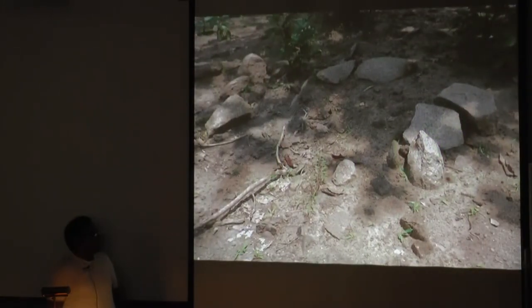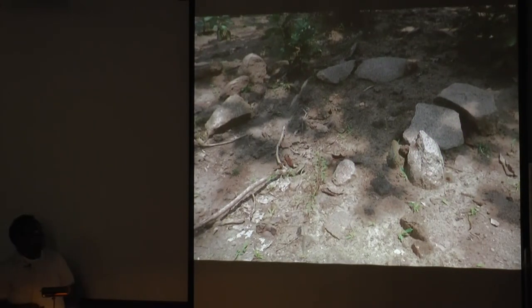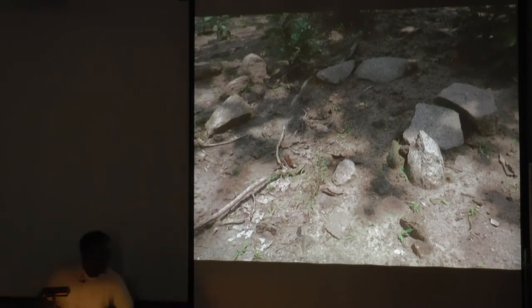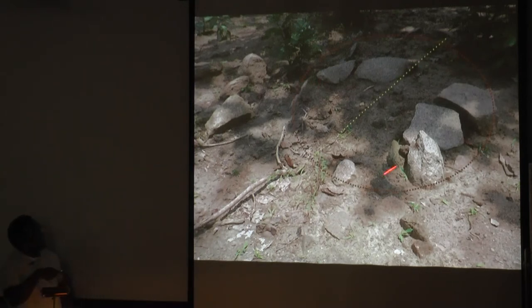And in there, because these sites are more or less intact, you would also see remains of furnaces like these. This was probably a furnace base supported by granite, and the place where the furnace would be is now packed with slag, and there are a lot of tap slags found here, which was probably where the slag tapping channel was. But we're not allowed to do an excavation by the forest authority, so we could not dig, and we had a forest tracker with us, always keeping an eye on us.